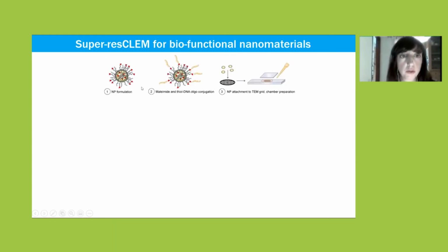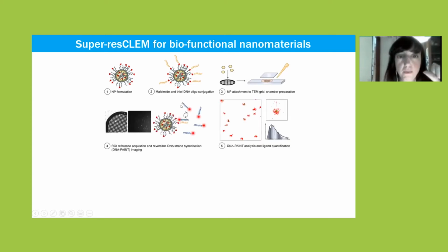So how do we do it? So we formulate the nanoparticles. These are polymeric nanoparticles. And then in this case, our ligand here will be the oligonucleotide sequence for performing DNA paint. So we have nanoparticles with different formulations, with different percentages of this oligonucleotide. And then we attach them on a TEM grid. We prepare the chamber with the imager that will allow us for the imaging of the ligands.